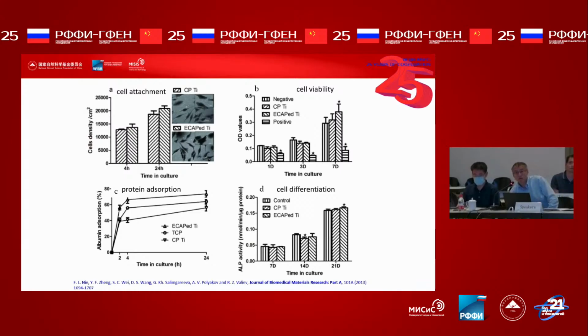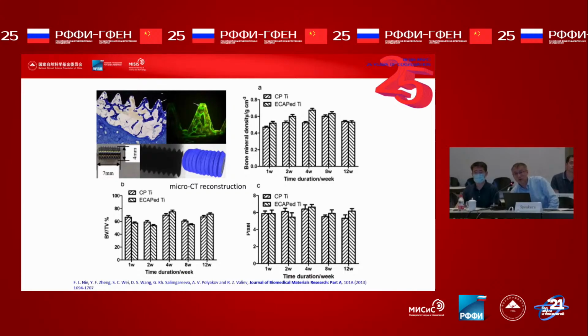As mentioned by Professor Valiev, after nanocrystallization of pure titanium, you can find that the ECAP titanium, the nanocrystalline pure titanium, has better protein adsorption properties. And if we do the animal test, next slide, please. If we implant the nanocrystalline pure titanium into the bone of the beagle dog, you can find that in the initial 4 weeks there is a very quick new bone forming ability.